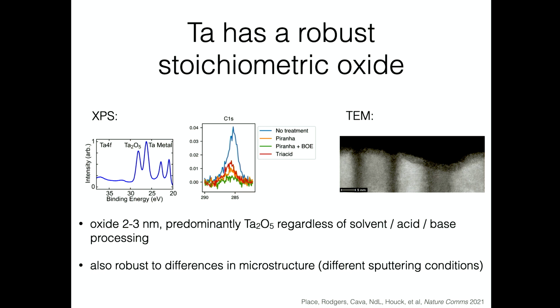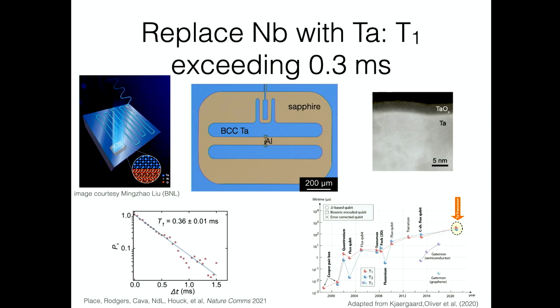And also, as advertised, it's an extremely robust material. So we can do things like, this is the carbon 1s peak in XPS. So it's sort of a reporter on how much hydrocarbons you have on the surface. And we can dip it in sulfuric acid and peroxide. We can boil it in perchloric, nitric, and sulfuric acid and do all of these crazy things to it. And the carbon 1s goes away, but the Ta2O5 always looks basically the same.